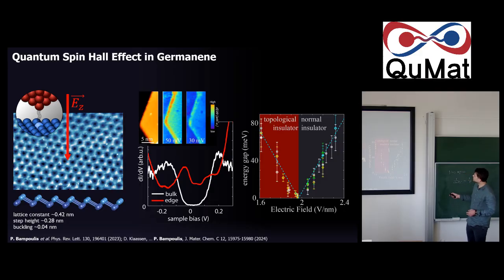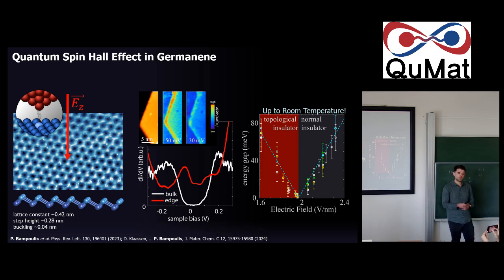So we can go, as you can see here, from a phase diagram, from a topological insulator with the edge states to a trivial insulator where these edge states are also gapped. And very recently, we also found that this effect, this switching mechanism, is also strong up to room temperature. So we can see, even though thermal convolution does not allow you to really resolve your gaps, you can still see the switching of the state on and off up to room temperature.